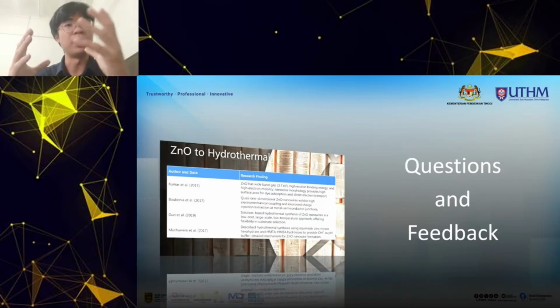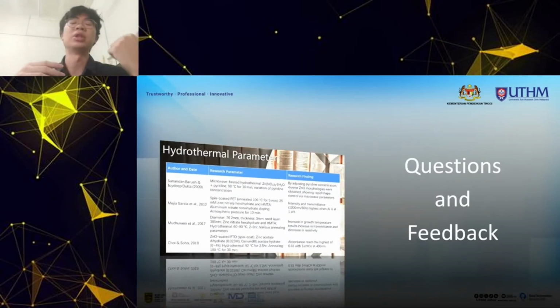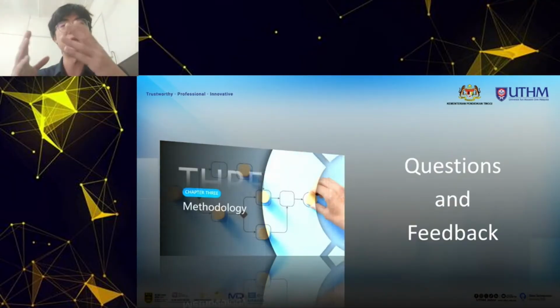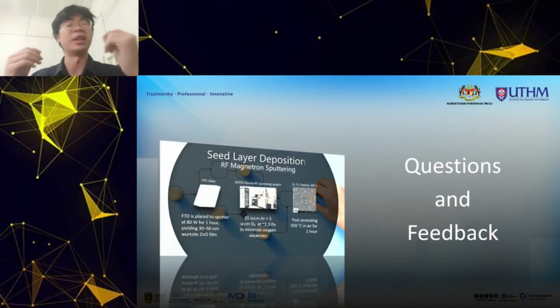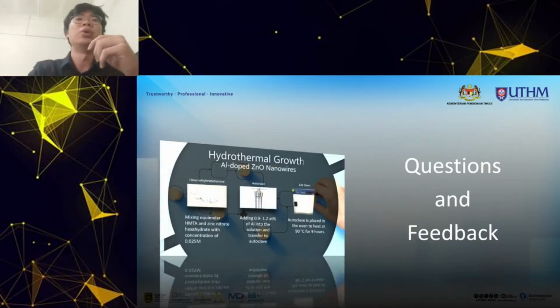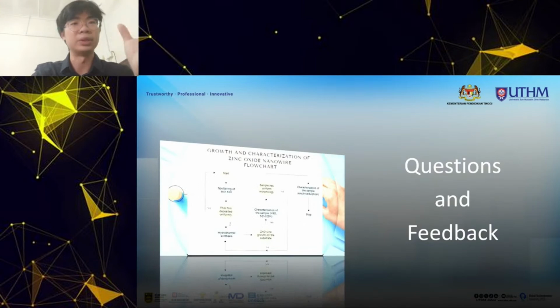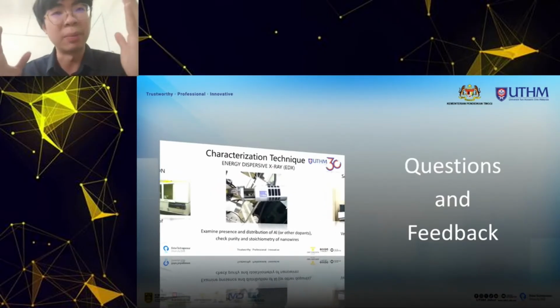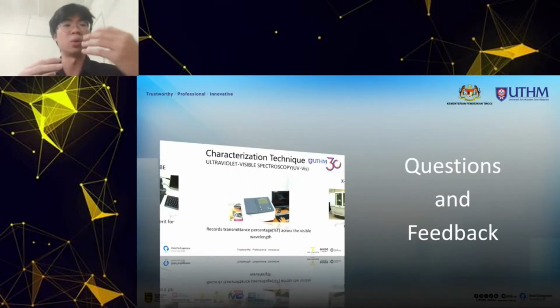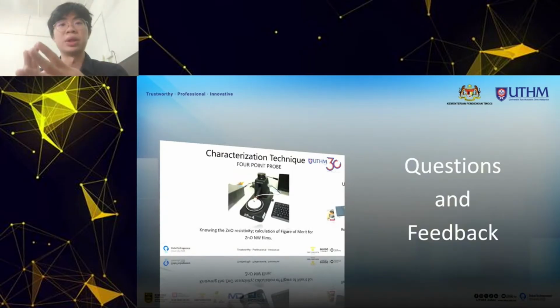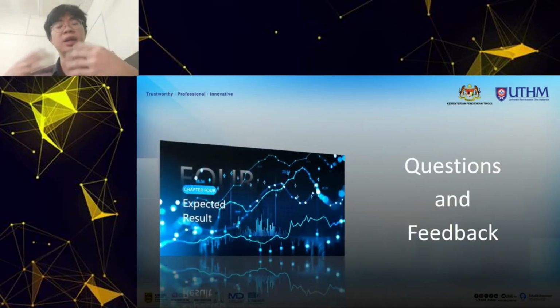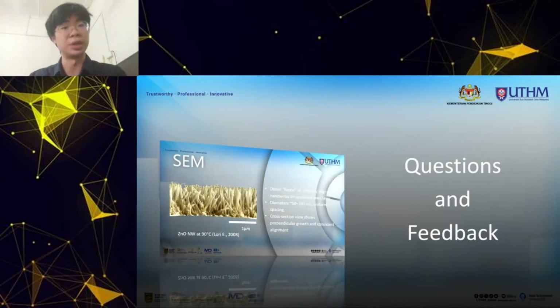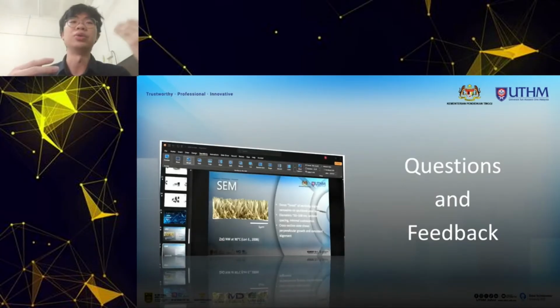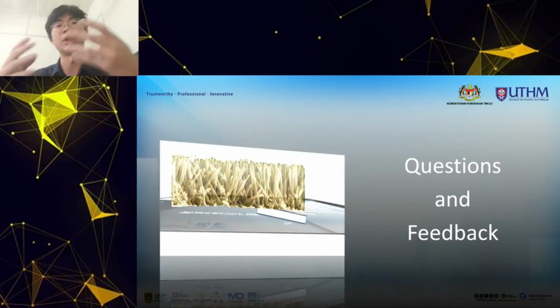So, I will correlate the doping levels with structural XRD, compositional EDX, optical UV-Vis, and electrical 4-point probe properties. And I will identify the optimum aluminium concentration, which is predicted around 1.0 to 1.1%, that maximizes the transparency-conductivity trade-off as quantified by a peak figure of merit. Achieving these goals will demonstrate the feasibility of a low cost, abundant aluminium doped zinc oxide nanowire, and this insight will lay a solid foundation for device fabrication and performance testing, ultimately contributing to more sustainable and scalable solar technology.